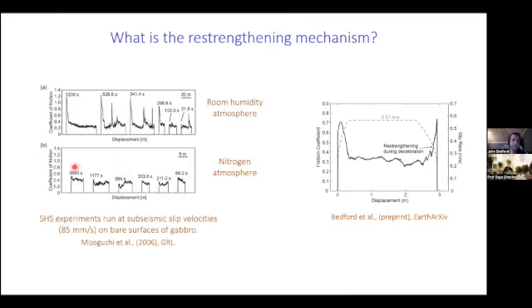But in the nitrogen atmosphere, regardless of how long they've been held, we don't see the same recovery of the peak strength in the gabbro bare surfaces that we do at room humidity conditions, which suggests there's a chemical effect that is causing the healing in these bare surface experiments. I should say they were conducted at slower slip rates than what I performed on the gouge. These were done at 85 millimeters per second, so more subseismic slip velocities. But they do show that we get a chemical dependence on this healing mechanism.